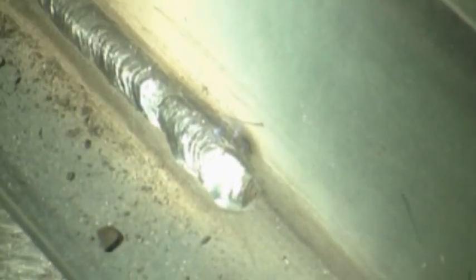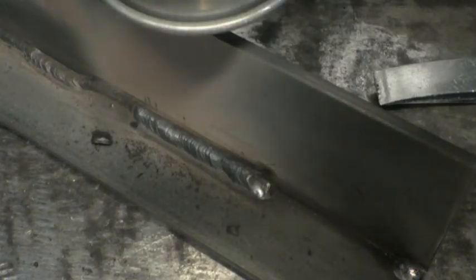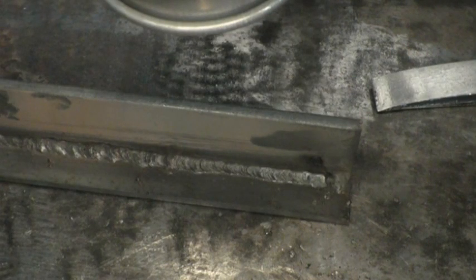It's actually bridged across the corner a little bit. You really want to avoid that. You want that weld to melt all the way into the corner. So you've got to be very careful if you start doing any weaving on a flat or horizontal. And in general, you need to be aware of what you're welding. Some materials just cannot get excessively hot, and weaving accomplishes exactly that. It makes the material a lot harder than it needs to be. Although for most mild steel that you would ever practice on in school, that's not realistically going to be a problem. So again, that's horizontal welding with stick and some of the basic things that you could in fact do wrong.